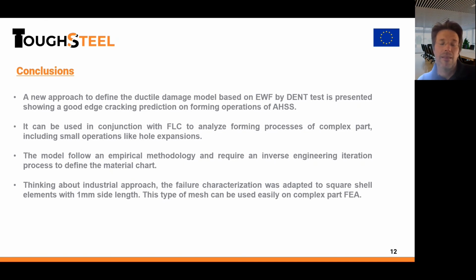The problem now is we are looking for a direct definition from the test, looking, for example, at the thickness strain, and only with this value trying to obtain the full parameters of the model. And also, thinking about the approach, the failure characterization was adapted to a square shell element with 1 millimeter element length, and we think that this type of mesh can be used easily in simulations of complex parts.